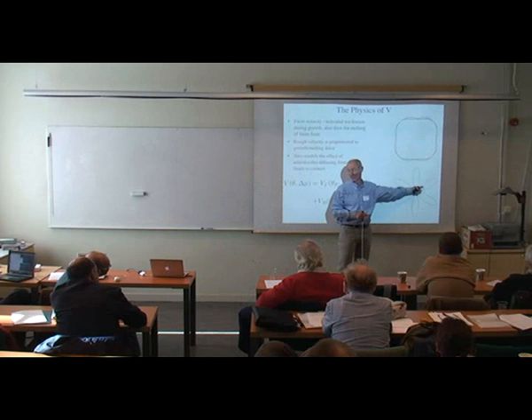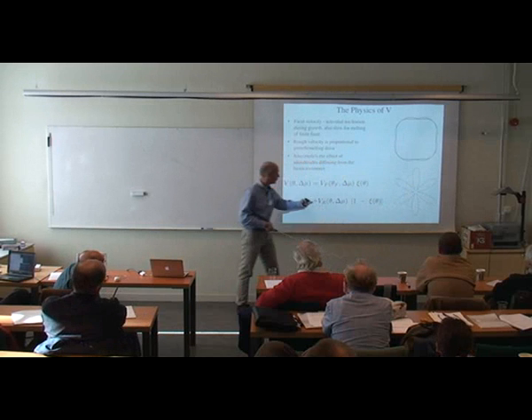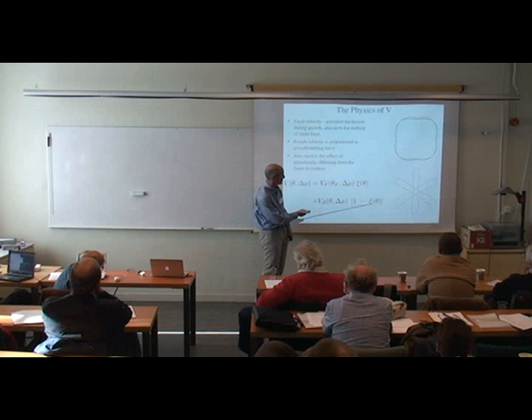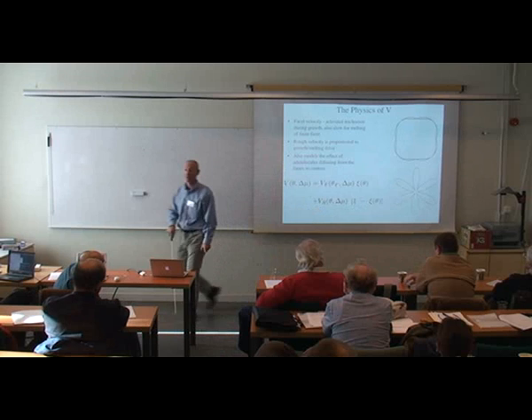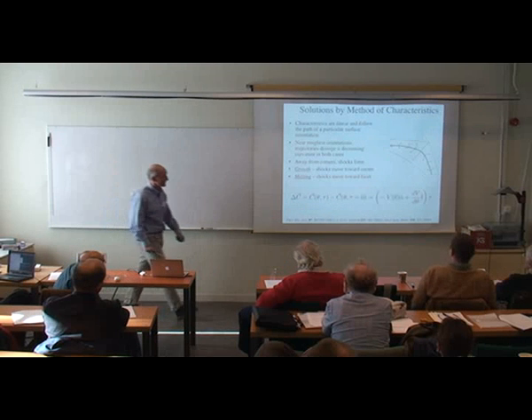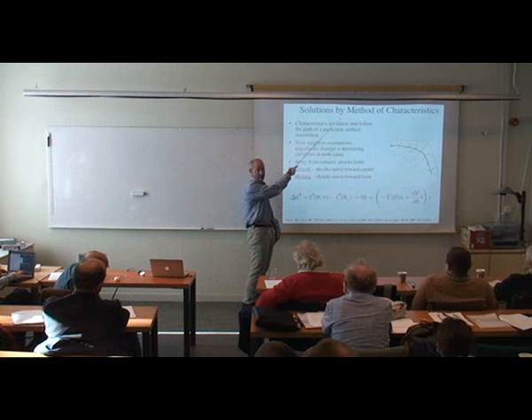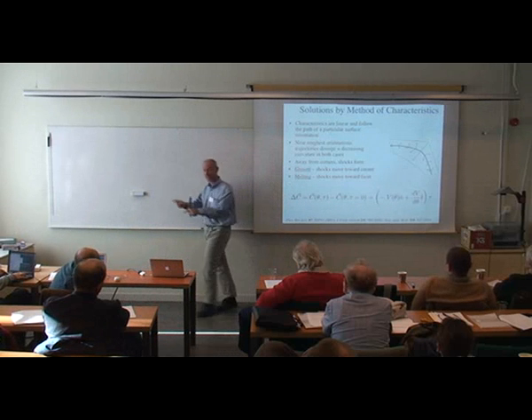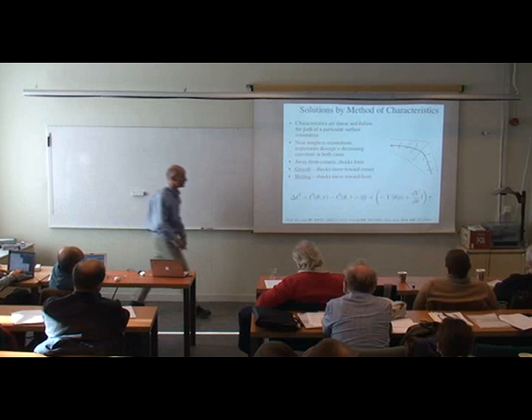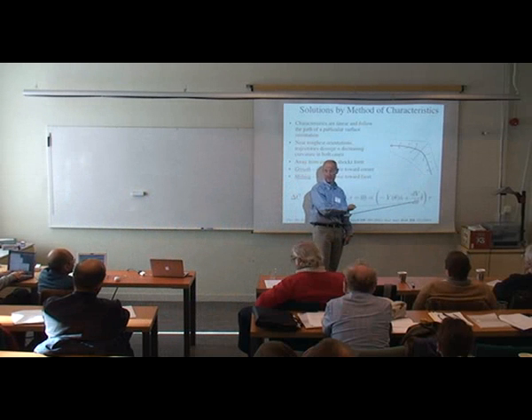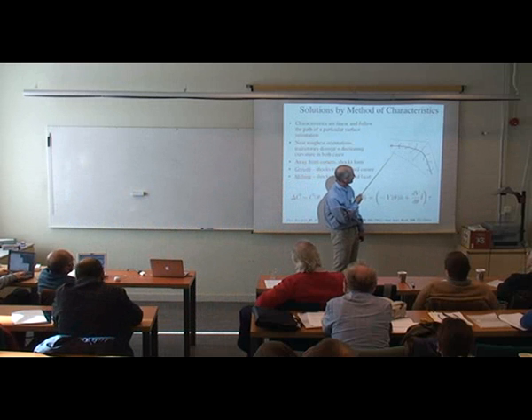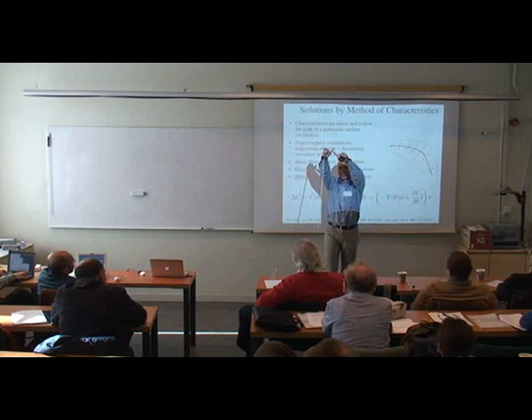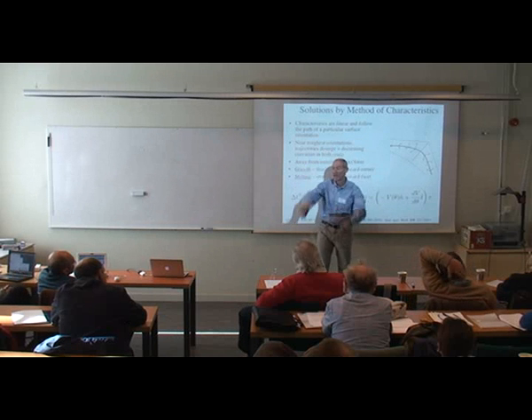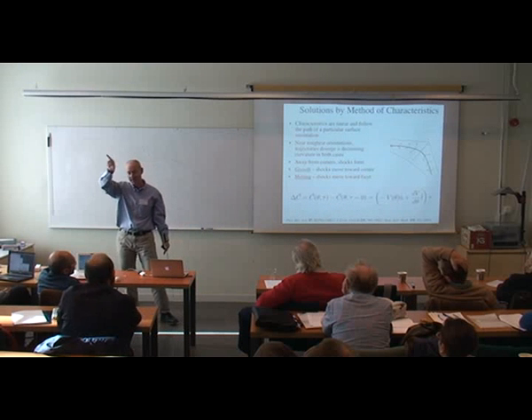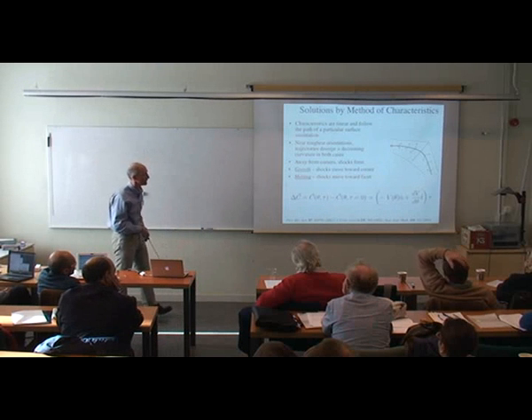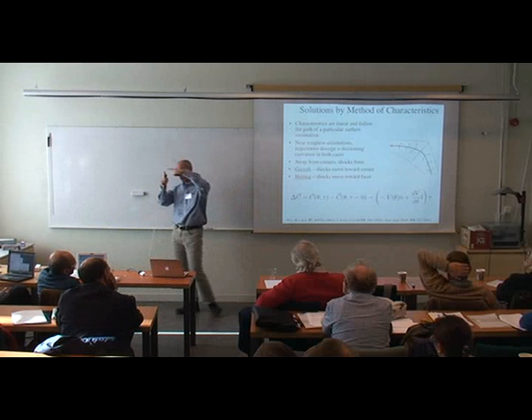I have 6 facets and 6 rough regions, okay? Fast growth, slow growth. Okay. That controls, if you will, the underlying molecular constituents, and these are the kinetics as you move around. That's the ansatz. And you can see, so you know that I can solve this equation by characteristics, right? And so the characteristics are straight lines with trajectories, and the magnitude of the trajectory depends on the physics underlying the kinetics of the crystal growth. And you can imagine then that surface orientations, which are fast, could collide, okay, competing for orientations on the surface, and these shocks create a discontinuity in the curvature, okay? And so that gives you an underlying edifice to study these corners that move, okay?